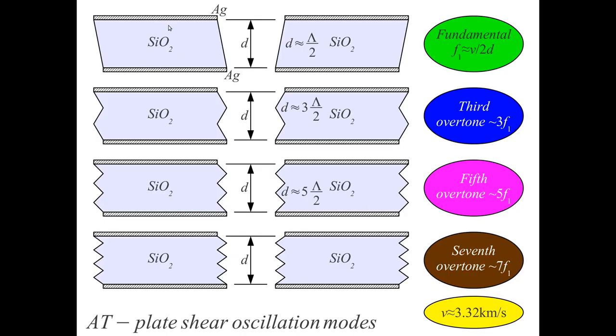Shear oscillation. What does that mean? Shear oscillation means that the plate is moving in this direction, left and right here, and this is the thickness. The thickness d defines the frequency. If we know the velocity of the wave, and the velocity for thickness shear waves in quartz is 3.32 kilometers per second, and we divide this velocity by twice the thickness, which is half of the acoustic wavelength in quartz, we get the resonant frequency. So for a typical crystal, we have 100 micrometers of thickness for a 16 megahertz fundamental frequency, 50 megahertz third overtone, and so on for the higher overtone modes.